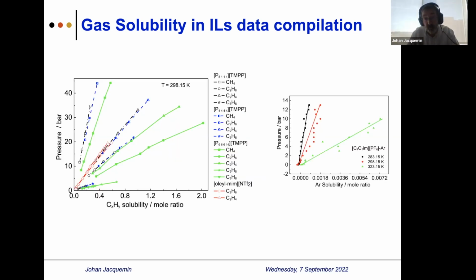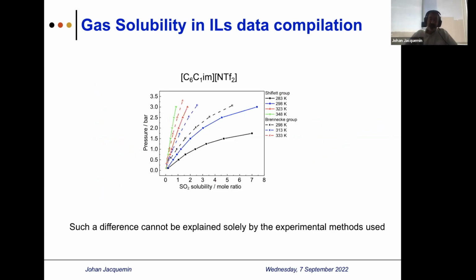Some of the data are measured by me, so that's not a group. Anyway, maybe it comes from the ionic liquids. More importantly, the IUPAC ionic liquid, hexylmethylimidazolium bis(trifluoromethylsulfonyl)amide, NTf2, has been measured with the same ionic liquid and the same purities by 2 groups, the Shiflett group and the Brennecke group. Of course, they used 2 different techniques: a Cailletet apparatus, and here a quartz microbalance. But anyway, one can see from this graph, if we look at the same temperature, the blue curve, for example, from the Shiflett group, and the white square from Brennecke, that the differences are very huge.